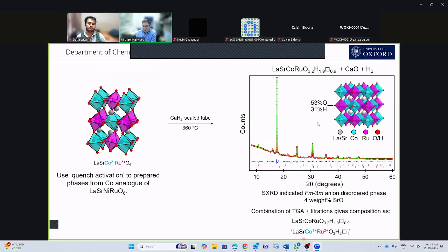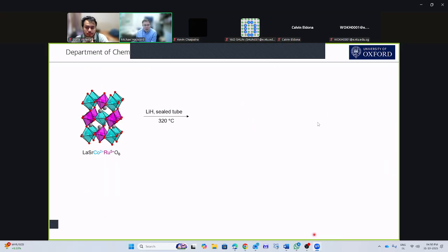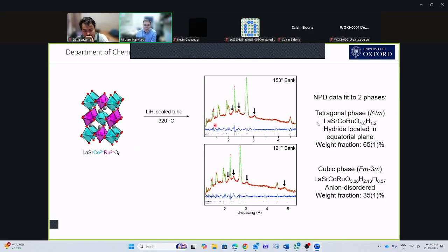So very close to LaSrCoRuO3H2. Okay. What I can also do is take lithium hydride with this material rather than calcium hydride, seal this in a tube, heat it to 320 degrees C, and now I'm showing you the neutron diffraction pattern. And what we see in the product of this reaction is I get two phases. A cubic one, a bit like this phase we saw before, and a tetragonal one.